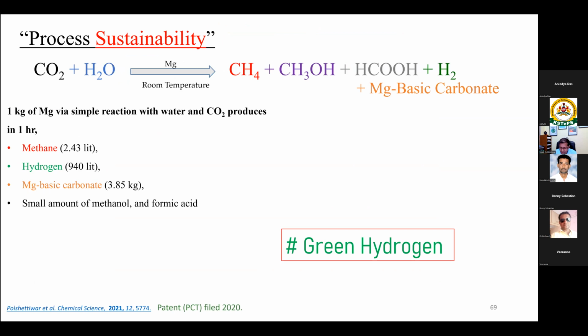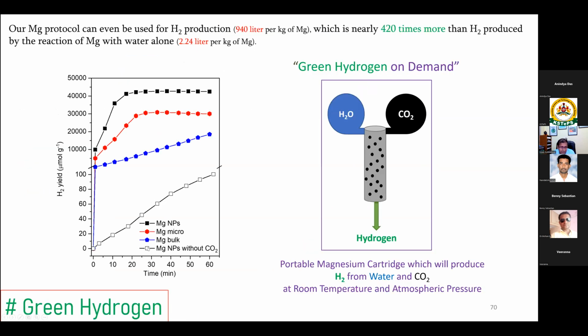In addition to that, we also showed that we can produce a large amount of hydrogen, 940 liters of hydrogen. Look at this data: if I use pure magnesium with water reaction, no CO2, then I only produce 2.24 liters. But as soon as there's CO2 in the reaction, then I produce 940 liters. There's a chemistry there, right?